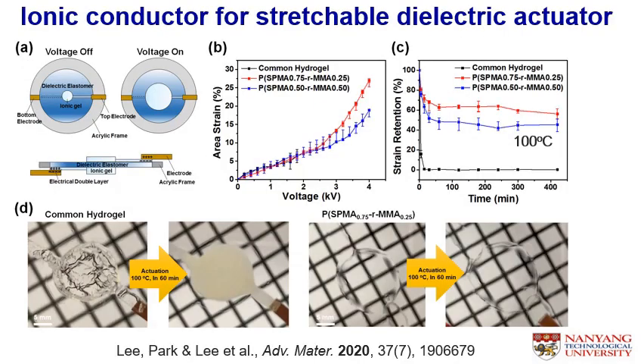This ionic conductor provides a good option for the dielectric actuator to function at high temperature. As a result, we can see that the strain retention can be maintained over 400 minutes when it's heated at 100 degrees Celsius, with the optimum performance achieved for MMA 25%.